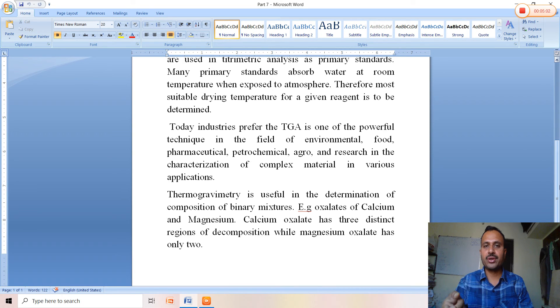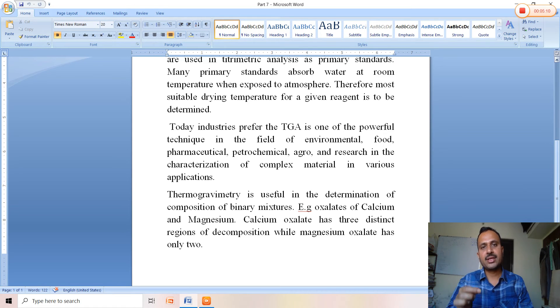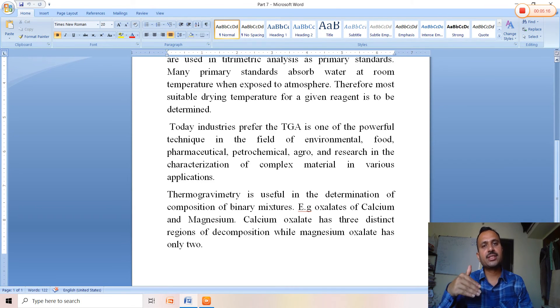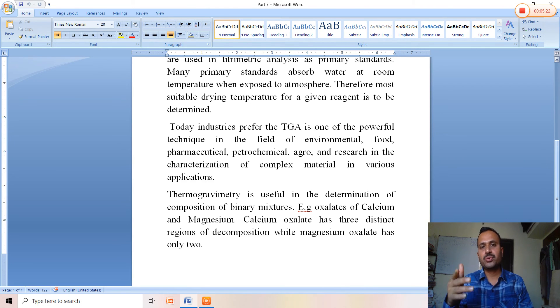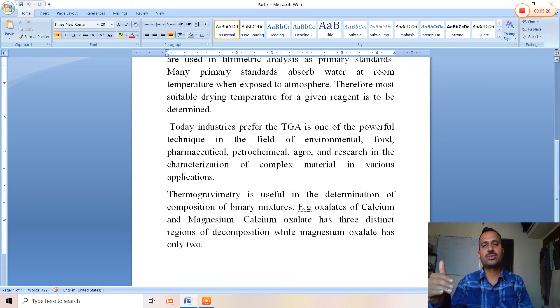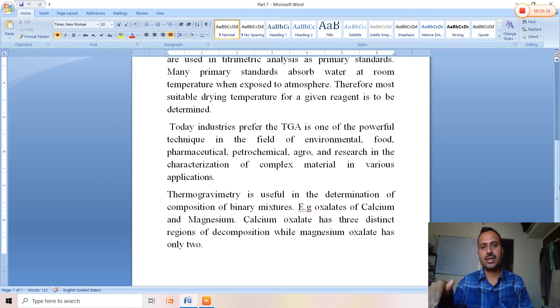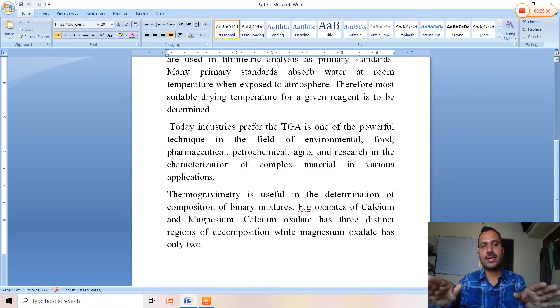When heat is applied up to 650°C to 800°C, the calcium carbonate decomposes and carbon dioxide is evolved. This is the most important distinction: there are three steps in the TGA curve of calcium oxalate monohydrate, while only two distinct decomposition curves are obtained for magnesium oxalate. This difference allows us to determine the composition of the binary mixture using TGA.